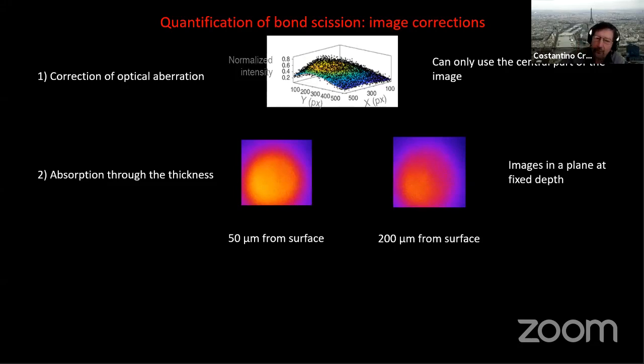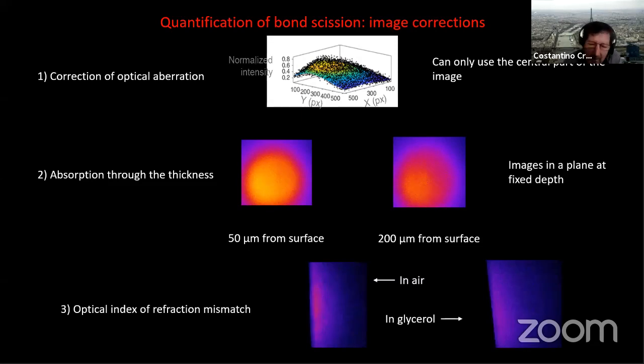If you do an experiment 50 micron from the surface, you have more signal than 200 micron from the surface. So you have to really correct for that: do a depth scan initially, and correct for the thickness you're going through. Finally, if you're measuring at interfaces, you have an optical index of refraction mismatch. If you're putting your sample in air, we realized that in air you have reflections that give you additional signal. If you actually use glycerol, which has a very similar index of refraction, you have, in this case, a realistic signal. So if you take all of that into account, you can have at least a realistic fluorescent signal.